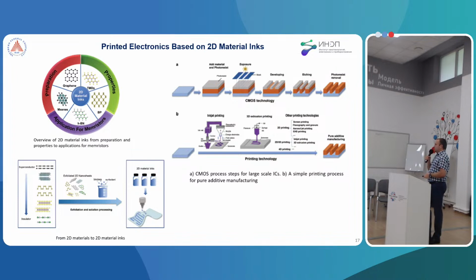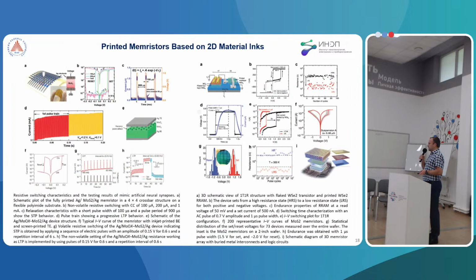Here is presented the preparation of 2D material inks from 2D materials, and results of producing these printed memristors. Resistive switching characteristics demonstrate that it mimics artificial neural synapses. Relaxation characteristics and current-voltage characteristics are presented here.